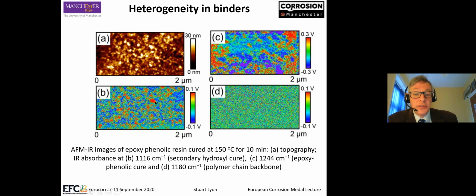Okay, so the resolution of this image is around 50 nanometers, and we can see very clearly these are micron resolution, and this appears to be associated with some of these nodules on the surface. If you look at this one here, this is the epoxy, also part of the epoxy phenolic cure reaction. Again, we're seeing chemical heterogeneity at a micron size scale.